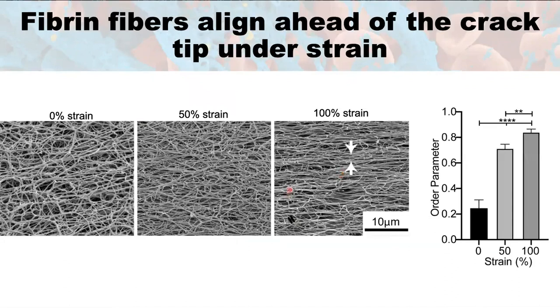We're also able to look at a larger range of strains in samples that were examined with scanning electron microscopy. And again, we see that as we increase the amount of strain, we do get increased alignment of the fibrin fibers. So that can help to inform the mechanism of what is happening in terms of the rupture process.